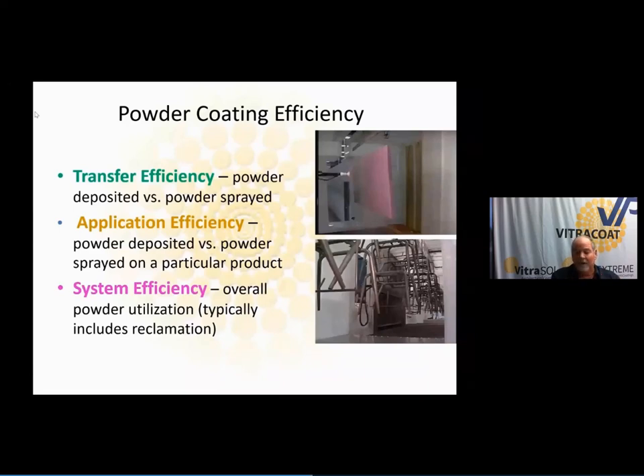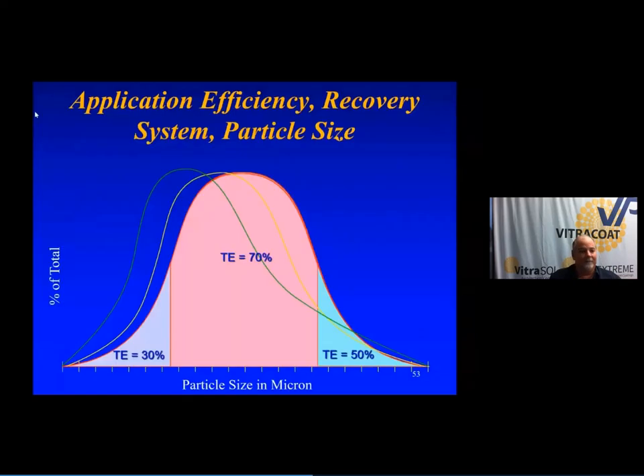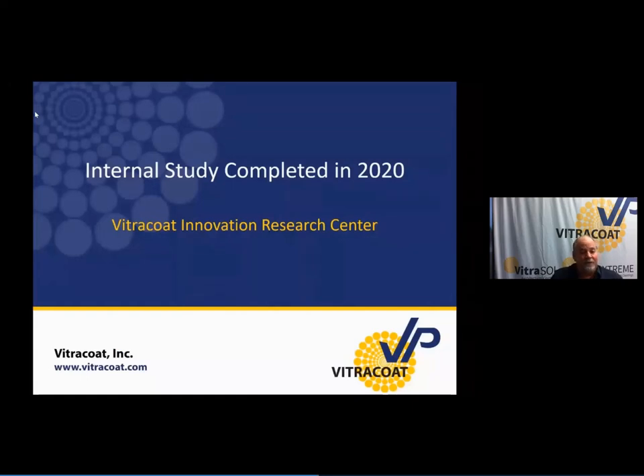There are a number of different variables that will impact that. And the reason transfer efficiency is important, specifically in a reclaim system, is because over time, the particle size distribution will move finer and finer because you have the optimal particle size that will attract to the part more readily. And then you have the breaking down of the particles as you're reclaiming them through the system. So I want to get as high a transfer efficiency as possible, especially in a reclamation system. Well, in a non-reclaim system, the value is different, but just as important.